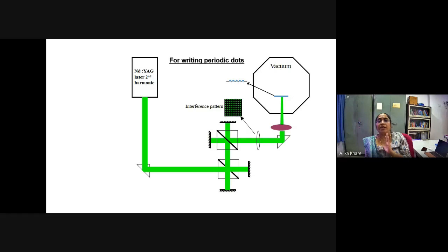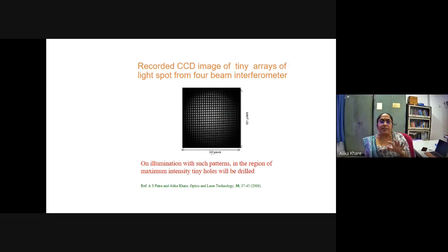Now this square array is allowed to illuminate the film, either in vacuum or in air, but we wanted to write it at the order of the wavelength, the periodicity of the order of wavelength. So we don't want the evaporated or ablated material to get redeposited, so we did it under vacuum. This is the interference pattern which we recorded, and then we illuminated it, and we could get this kind of matrix, in the scale of 20 micron by 20 micron.